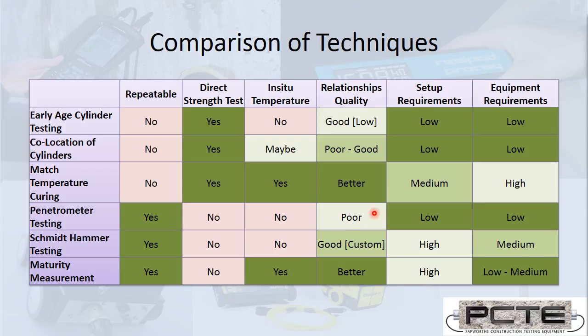Now the relationships are going to depend upon how well we take sample compressive strength tests and relate them back to our real concrete used on site. So the first point is, whenever we're doing a correlated method, you need to establish that relationship between a certain concrete mix and a certain technique of strength measurement. So this means that for where we're building custom curves, particularly Schmidt hammer testing and maturity testing, there needs to be quite a large test mix done to build the curve that is then used on site. Then finally, once we're out on site, we need to have the sensors installed or the tools to use out on site. That's where I place the equipment requirements.